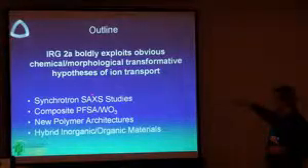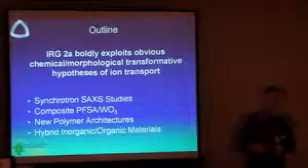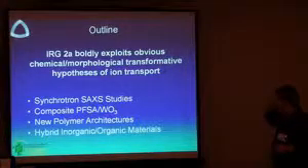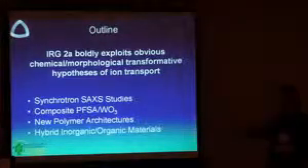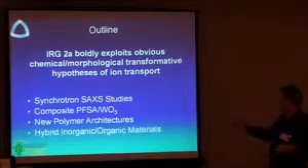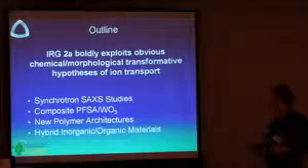And so basically we divide our efforts into 4 parts. One is basically to develop new techniques based on very rapid synchrotron small angle X-ray scattering. Another is a very, very old idea that originated between myself and John Turner back in 1995 to look at some of the tungsten oxide materials that have come out of NREL's electrochromic program and see if they can actually hold on to enough water in these PEM materials that they'll still conduct protons at high-end dry conditions.